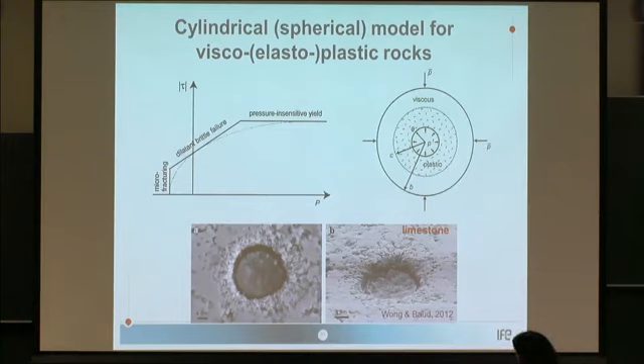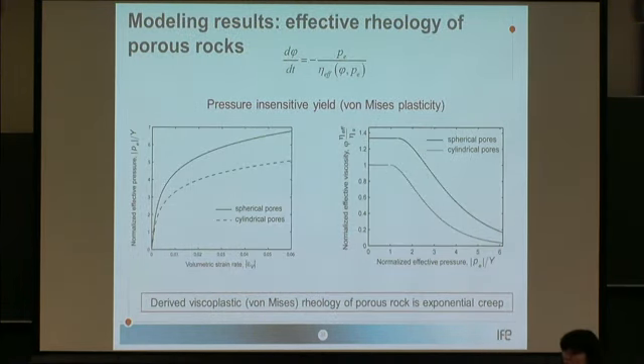And we assume that plasticity on the pore scale is driven by Griffith's criterion, which we approximate with three linear simplified functions. This is pressure insensitive yield given by the standard von Mises criterion. This is dilatant brittle failure, which is described by Mohr-Coulomb failure. And this is microfracturing, which is just a closing cap on the Griffith criterion. So we treat each of these cases separately, but we need this linearization to get analytical results, because elastoplastic or viscoplastic solutions are already difficult by themselves, without adding extra nonlinearity.